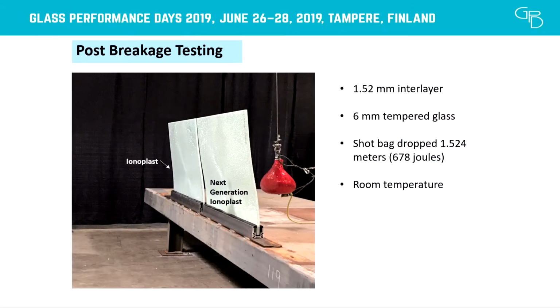Now I'm going to move on to post-breakage testing. We've conducted some room temperature post-breakage testing. We have elevated temperature post-breakage testing underway, and we wanted to ensure that they were going to be comparable. So we did the same testing that we've done with our Ionoplast in the past, where we used 6 millimeter tempered glass and a shot bag dropped at 1.5 meters. This is at room temperature, and you can see that they have pretty similar performance. They both, after breaking, still stand up.